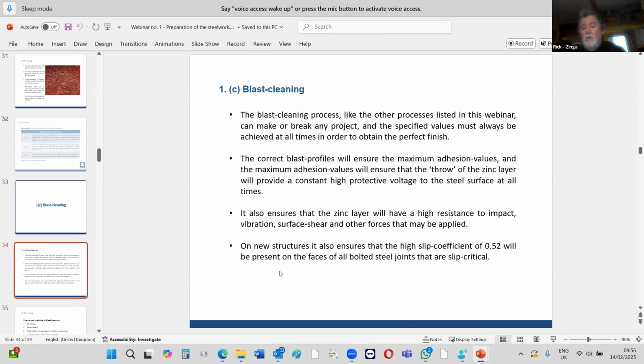Another thing with the Zinga, on a blast clean surface, you got your peaks and valleys, and the Zinga is going inside the valleys. This is why when you have an impact on a bridge from a truck, and the guy said, wow, the zinc didn't come off, because you have a profile with the zinc. If you have an impact, it's pushing the zinc inside the profile. It's not coming across the top and ripping it off. And even if they have a shear factor, we saw this in Singapore, a truck hit the crash barriers, and they had been done with Zinga that had already been recoated a few years beforehand on the highway. And all it did, it sheared off the top layer of Zinga.